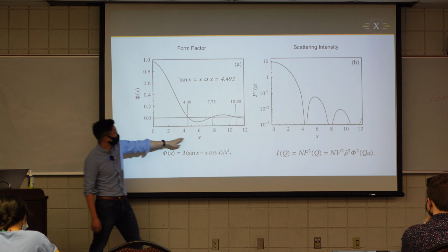It can be a particle, it can be a plate, or it can be a rod. So this happens at very low Q. And you need to make sure your 2 pi divided by Q is larger than the expected size scale of your structure to observe the Guinier region. So if your instrument can only measure to here, let's say here, you will never be able to see the appearance of this region. Okay? And it's generally harder to measure larger features, because the bigger the feature, the more the region shifts to even lower Q. That challenges how we can measure it using our instrument here or at the synchrotron.